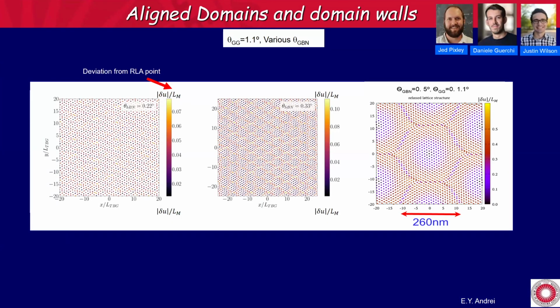And here we just plotted, okay, how far are you from rigid lattice alignment? At 0.22 degrees, you see hardly anything. You get closer, 0.33 degrees, something starts showing up. At 0.5 degrees, which is 10% away from rigid lattice alignment, you see a nice domain forming. And in this domain, we have 1-to-1 alignment. And you see the color scheme here tells us that the redder you are, the larger the strain. So basically, it stretches until it doesn't pay anymore, and then it gives. And that gives you a domain boundary, and then the whole thing starts over again. So this is the basic idea.